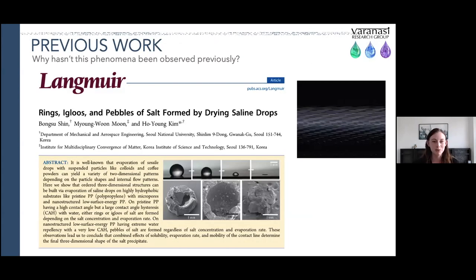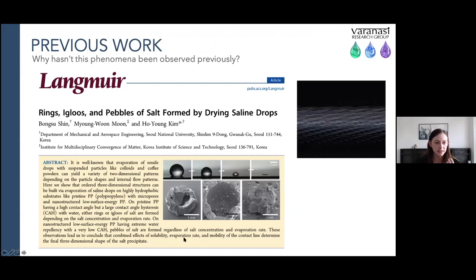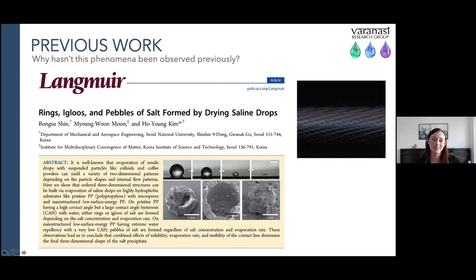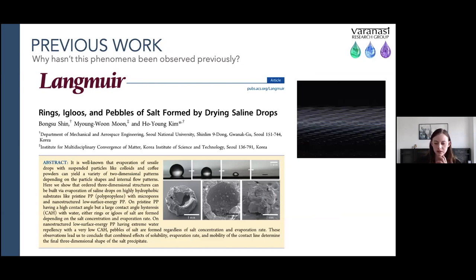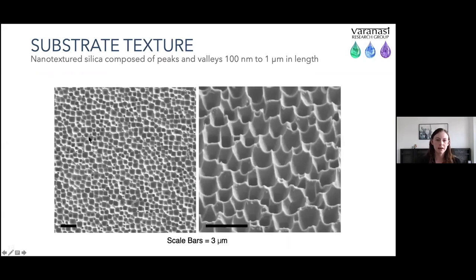This is clearly a very unusual phenomenon, which raises the question: why hasn't this been observed previously? There's actually an article in Langmuir published a couple years ago looking at formation of salt structures on superhydrophobic surfaces using the same chemistry and temperatures I'm using — yet they don't see what I'm seeing. The answer is the texture: they're using a microscale texture for their superhydrophobic surface, whereas I am using an actual nano-textured silica with periodic peaks and valleys at a very small length scale.